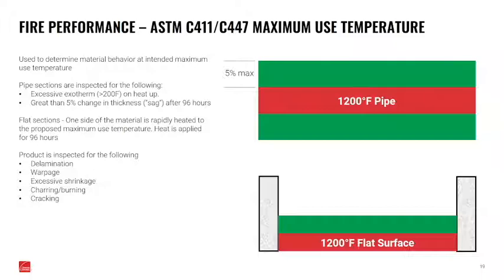So what we're looking for there is we'll take the insulation and actually install it on a pipe, and that's the top section you see here. We'll have a 1200 degree pipe. We'll install the insulation on that pipe while the pipe is still hot. And what we're looking for is exothermic. We don't want that pipe to rise in temperature more than 200 degrees higher than the pipe temperature.